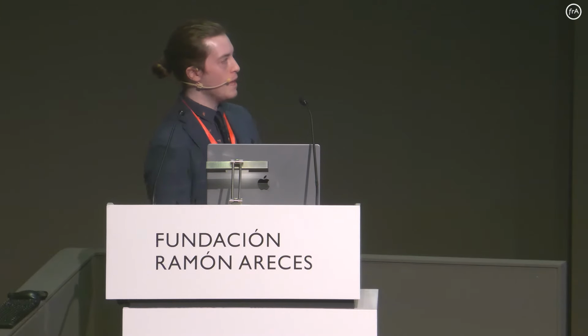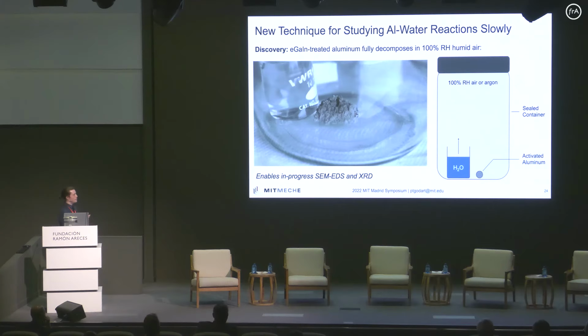I discovered a new method for studying this aluminum water reaction. I could actually get these aluminum pellets that were treated with the gallium and indium to spontaneously disintegrate and react with water vapor. And what this allowed me to do was sort of pause the reaction at various stages and then use standard materials characterization techniques like scanning electron microscopy and X-ray diffraction to really figure out what's actually going on in this reaction.